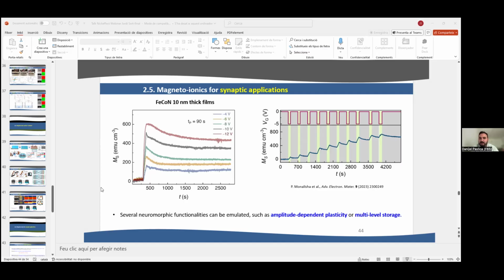Yes, we do have. Magnetoionic materials often suffer from limited cyclability or endurance. So how many cycles should a good magnetoionic material withstand to be marketable? Yeah, so for example, in our laboratory, we have reached several thousands of cycles. Probably you can induce more, but we just didn't do it. Maybe we can reach 10 to the 4, but it takes a lot of time, maybe more than 2 weeks, because this is not super fast.